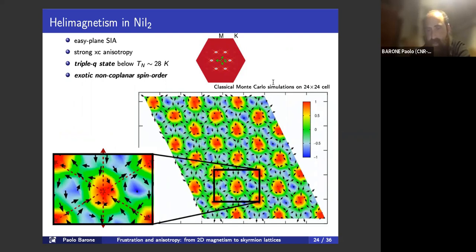So here again, I'm showing the spin structure factor. And you see here there are 6 peaks. Each pair of peaks corresponds to a single Q spiral. And this is a realization of a triple Q state, which can be thought of as a superposition of the 3 spirals, all simultaneously. The point is that if you look now at the snapshot of the spin texture at low temperature, we have this very exotic lattice, where you can see that there are strong cores with the magnetic moments pointing perpendicular to the lattice layer, which is a contradiction with the fact that we predicted for this system an easy plane single ion anisotropy.